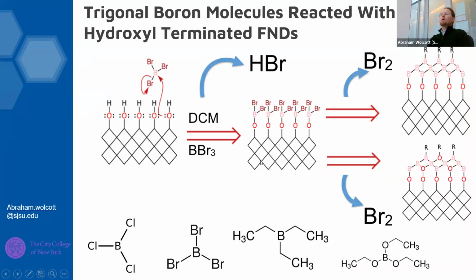Here's another cartoon. Again, we're using this alcohol-rich diamond, which is doing a nucleophilic attack on our boron center. You would have a leaving group of hydrogen bromide. You've now formed a carbon-oxygen-boron bond, which is an organoborate. The chemistry continues, forming some boron-boron bonds, and some of the remaining bromide or chloride groups are still dangling on the surface, and then you can continue on with your chemistry.